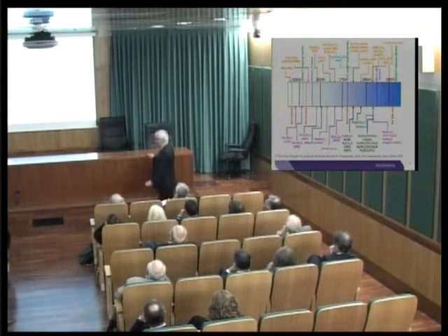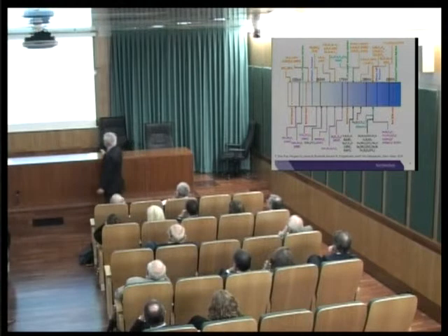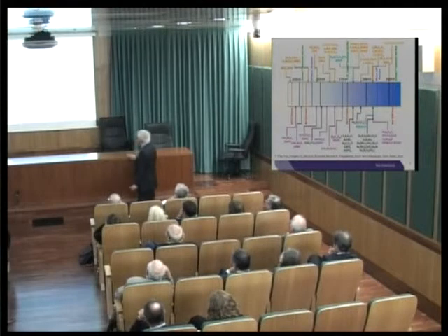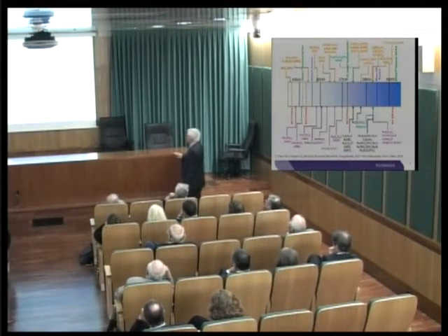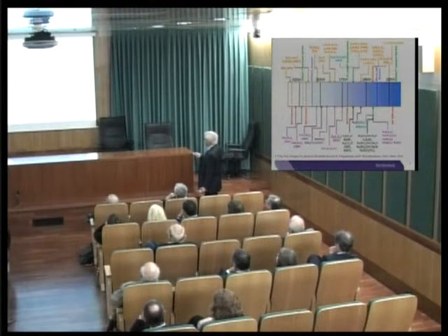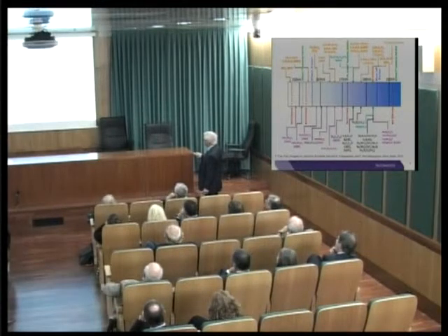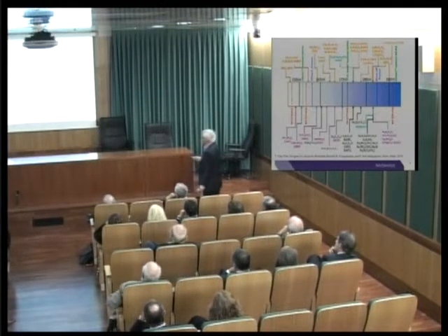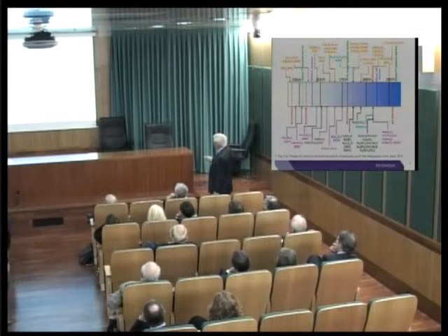Recently, Shiv and I and a few others have published this paper where we've just, in the last 15 years or so, there's been many materials now designed to function in the deep UV. Let's just look at a few of them and some pointers. This is below 200 nanometers. And this would be, for example, for an all-solid-state device if you had these materials. This one is the excimer laser at 193 nanometers. Here's the 157 nanometer laser, for a fluorine excimer laser.